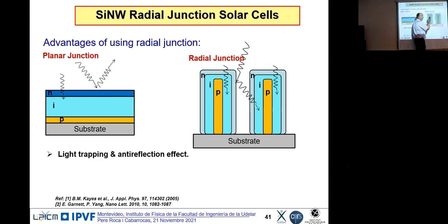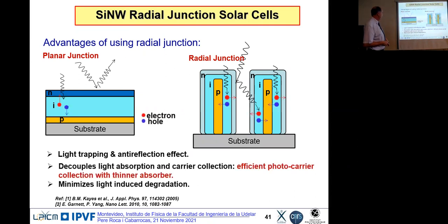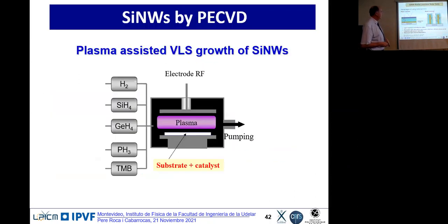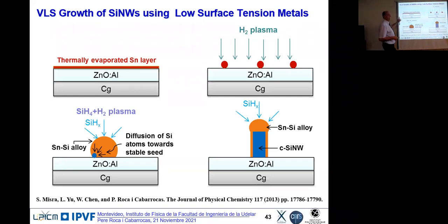So it's electrically thin, less than 100 nanometers in diameter. So you have a strong field which strips the electrons and holes and prevents recombination. So you use less material, and you can make a device which is efficient. And that's what we have been doing for a few years in the lab, using the same reactor, using metal catalyst